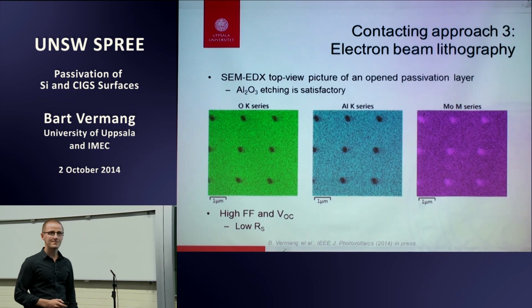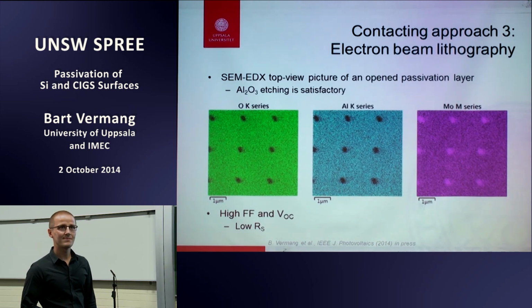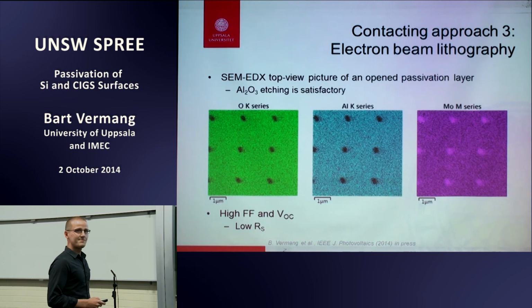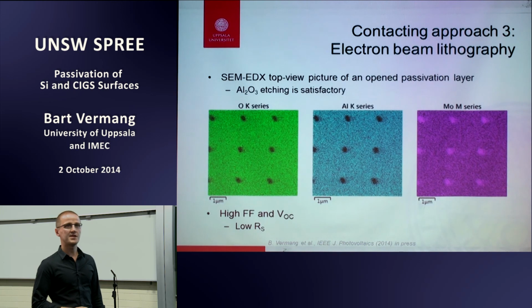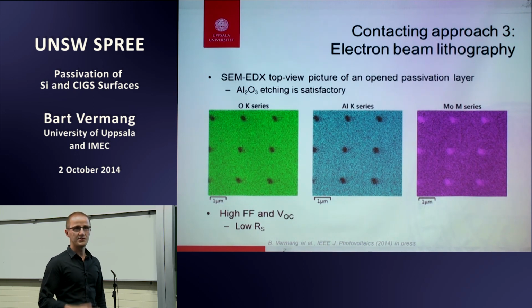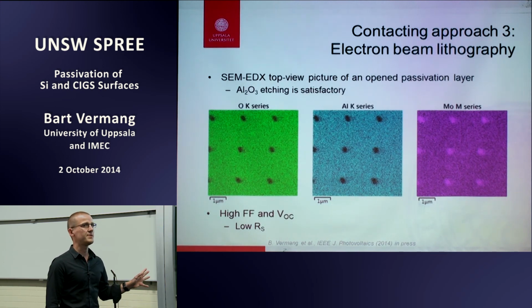Is there a molybdenum selenide layer between CIGS and molybdenum? In this context, we definitely still have molybdenum selenide interfaces, which you need for good contacting. However, you can't see it on SEM pictures or whatever because we're doing co-evaporation. It's quite thin. If you do sputtering at high temperature, then you always see this very clearly. So you can't see it very well here.